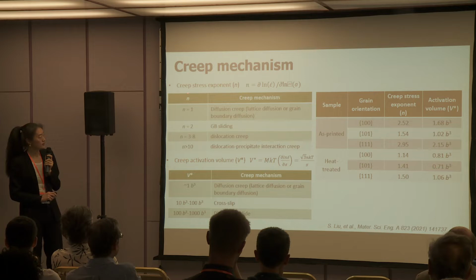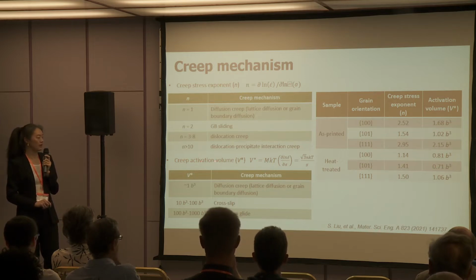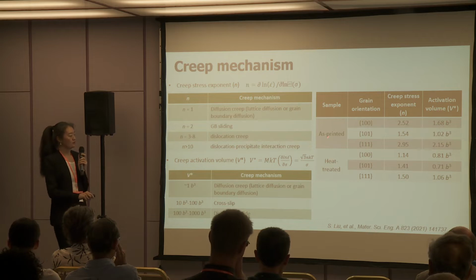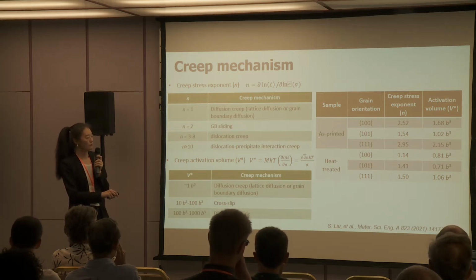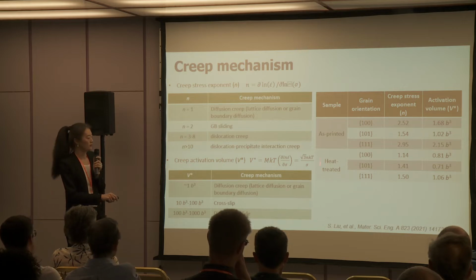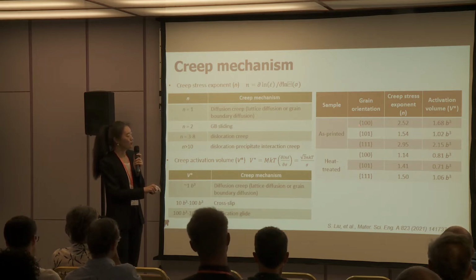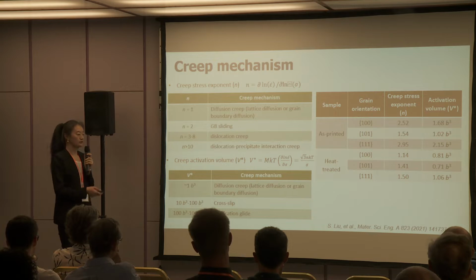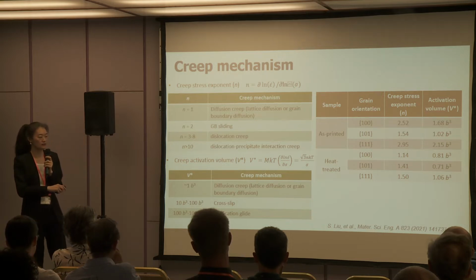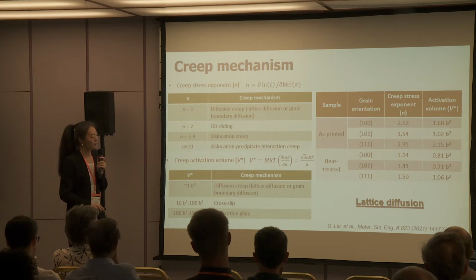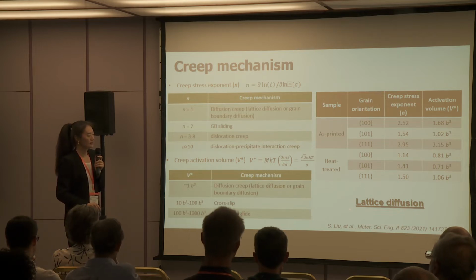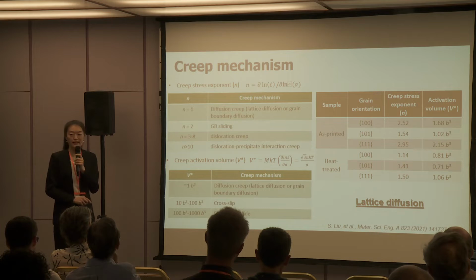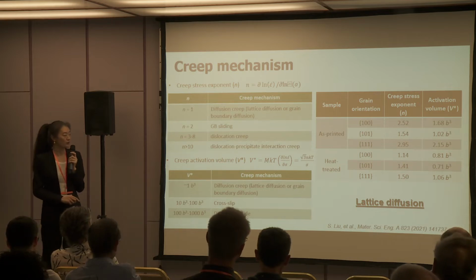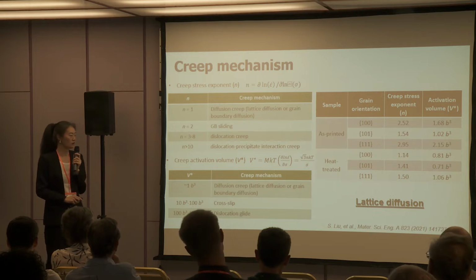Then we calculate the creep stress exponent and also the creep activation volume. I'll not go into detail here, but we can see the results. For both printed and heat-treated materials, the 100 orientation has the middle value, while 111 now comes to the highest. So it's a different order compared to the hardness and the elastic modulus. And the creep in this high entropy alloy is mainly governed by a lattice diffusion mechanism.